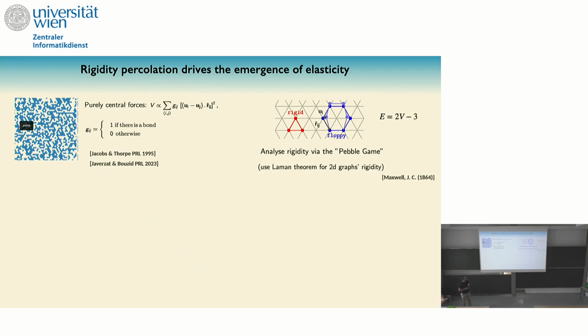So if you have more constraints than degrees of freedom, then your system or your cluster is rigid. On the other hand, if you have a system that has more degrees of freedom than constraints, then your system is floppy. You can deform it without any energetic cost. As I told you before, there is a well-designed algorithm called the pebble game. Doesn't matter the name, but this is a fast algorithm that goes through all your cluster and tries to identify where is the rigid cluster and where is the floppy cluster.